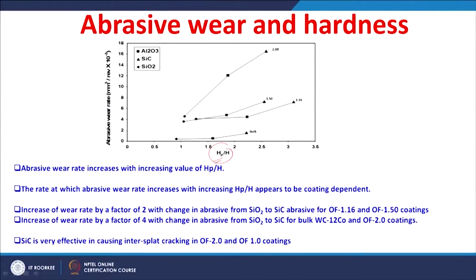So, it is very important to understand this with respect to the hardness of these abrasive particles used. In this study, a ratio of the hardness of the particle to the hardness of the coating is studied with respect to the abrasive wear rate. You can see the abrasion wear rate as a function of this hardness ratio of the particle to the target. The abrasive wear rate increases with increase in value of this ratio for any abrasive, but the rate at which the abrasive wear rate increases is different from one particle to another particle.